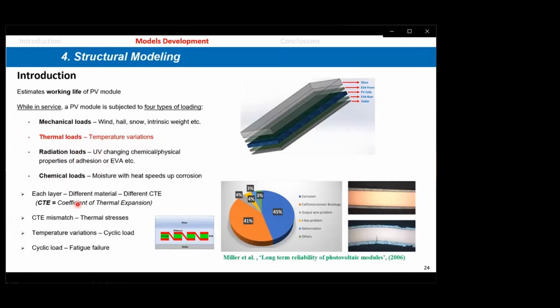And thermal loading, of course, because of the mismatch in the coefficient of thermal expansion between the different layers constituting the panel, obviously you're going to develop thermal stresses, and they are cyclic, because you heat and you cool, you heat and cool. So these are cyclic loads, and these cyclic loads will lead to fatigue failure. So now in this case we are including the copper ribbons, as you can see, as an additional element compared to the first simulations where we looked at only the temperature distribution. Here we're looking into mechanics, and in particular the mechanical and fatigue behavior of the copper ribbons.